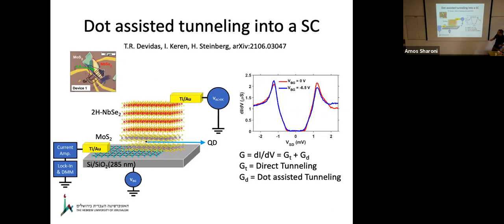And the device that David built was built from graphene. On top of graphene, there was MoS2, and on top of MoS2 was NbSe2. So transport took place through graphene, tunneling through the MoS2 with a certain transport channel dominated by a single defect. And I'm going to show you how we know it was a single defect.